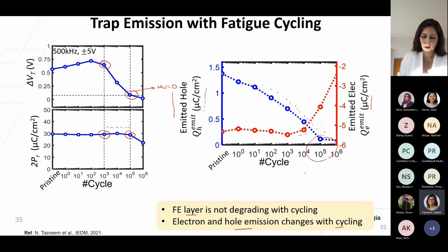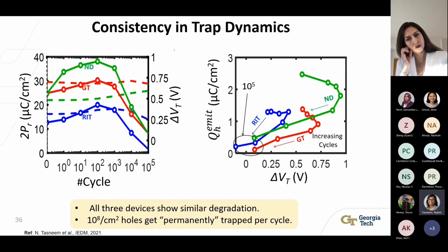Interestingly, these results are consistent among other different ferroelectric FETs. So we did this same experiment on 3 HZO N-type FeFETs fabricated in 3 different facilities: Notre Dame, Georgia Tech, and Rochester Institute of Technology. The dotted curves here show the evolution of 2Pr with cycling, and the solid curves indicate the evolution of the memory window with cycling. The first figure shows that all 3 devices show a similar degradation mechanism beyond 10^3 cycles. The second figure shows that as we keep on increasing the number of cycles, the memory window for all the devices decreases, and it becomes almost 0 at around 10^5 cycles, which is the same point where the amount of emitted hole also becomes 0. So this indicates that with cycling, additional charges are getting permanently trapped and not getting emitted, which means they're getting trapped into states which have a longer lifetime.